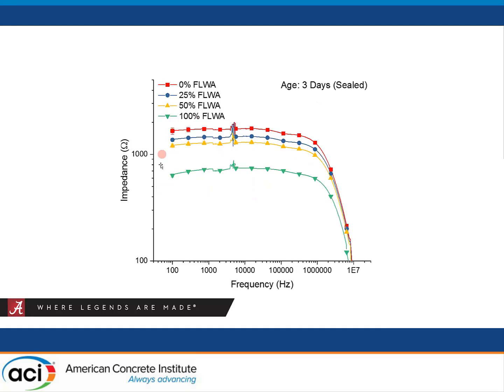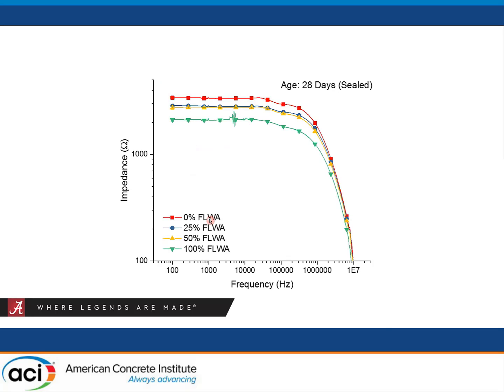We go to 3 days, and the scale of the y-axis will remain the same for all these graphs. And you see the resistivity increases overall, which is expected, where our 100% lightweight is significantly down here. All of this data is an average of 5 samples for each mix. And so you can see here you have error bars, and we have rather consistent measurements. Then we get to our 28 days sealed.